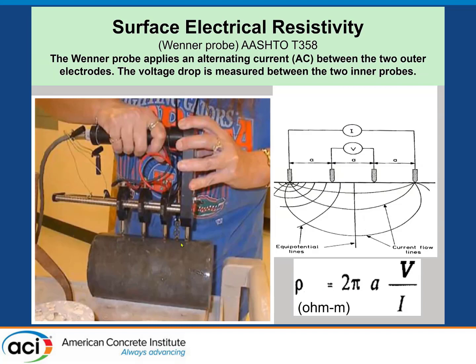Now, the trouble with surface resistivity, in my opinion, is that it is subject to more issues, because the surface needs to be adequately saturated and not carbonated, and a whole bunch of other issues need to be addressed before you can get useful measurements. So the other one, bulk resistivity, you're measuring right through the whole cross-sectional area. This is you're only measuring a surface value.